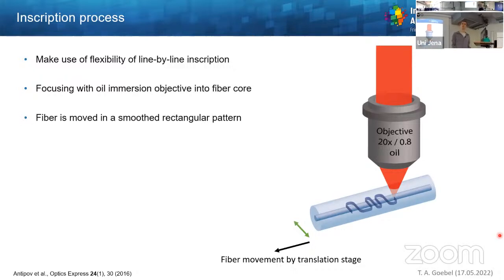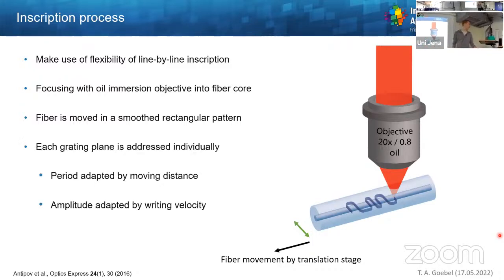But not only this, the amount of refractive index change we induce depends on the speed at which we are moving across the fiber core. So we can also adapt the speed for every layer according to the refractive index change we want to address. And when we do both together, we can realize the aperiodic fiber Bragg grating inside our fibers.